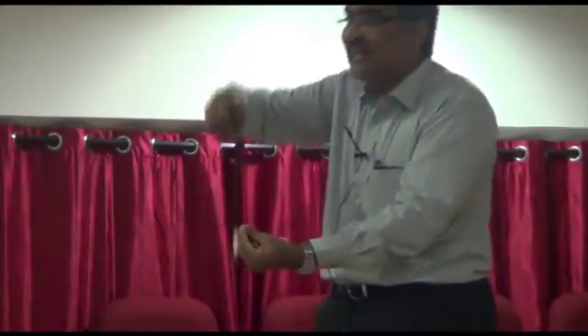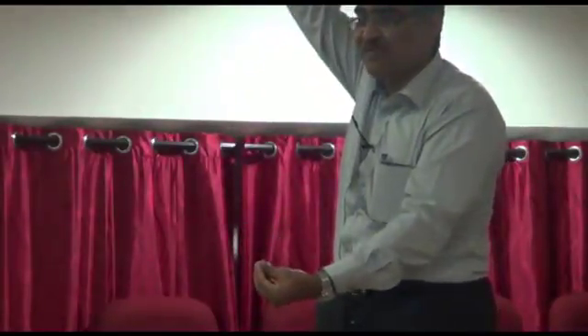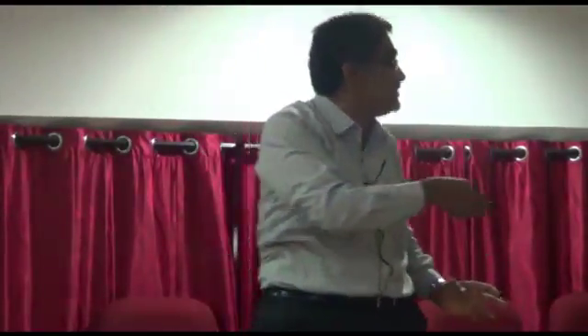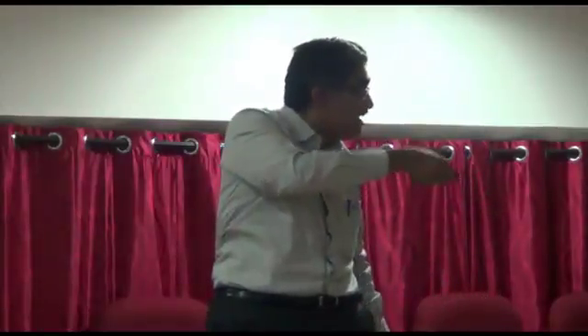So now, these walls, we realized, were actually nothing but... Later we thought it was just a strain relaxation wall. Then we realized it was actually those screw dislocations I talked about. Those screw dislocations, earlier just threading like this and becoming a dislocation inside the film. Now what we are doing by the kinetics, we are actually opening it up. So these are called open screw dislocations of these materials. So at the bottom of each of these holes, there is a screw. There is a step. There is a screw like this.